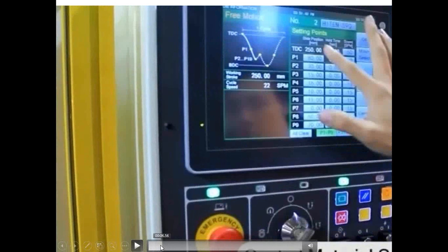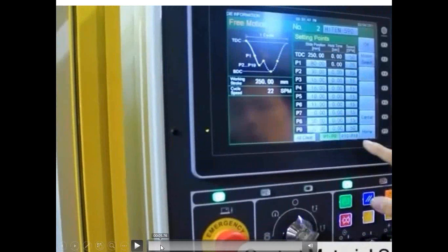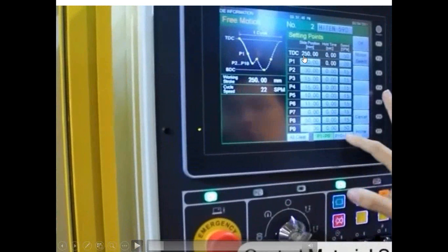So what we actually have here in looking at this profile, we're still starting up at the 250 millimeters. We start going down rather quickly down to 80 millimeters. Now I believe this is in a 10-step process, and really where we're looking at the action happening here is when we get down to 10 millimeters above bottom dead center, then we're going to go up a millimeter. And that's really going to allow your material to, and this may not be the technical term, kind of relax for a second until we then bring it down to bottom dead center. And that's where you're really taking out the spring back.